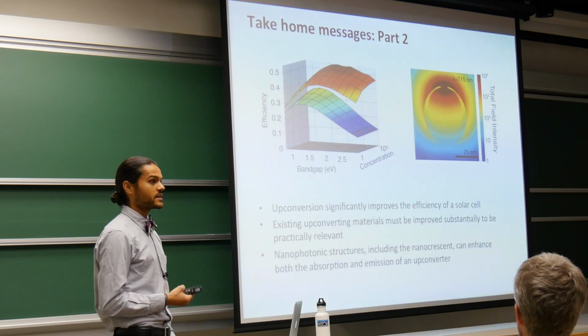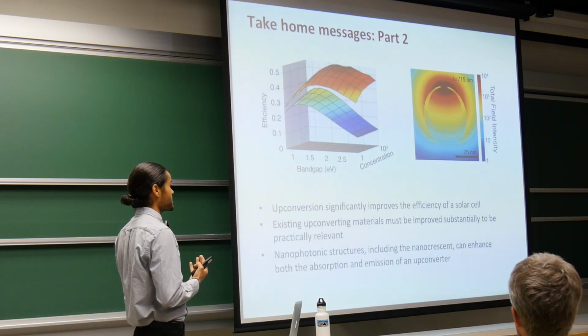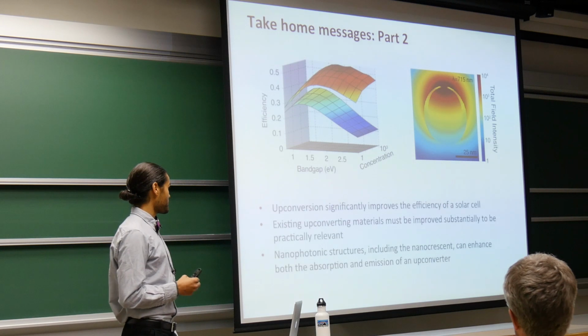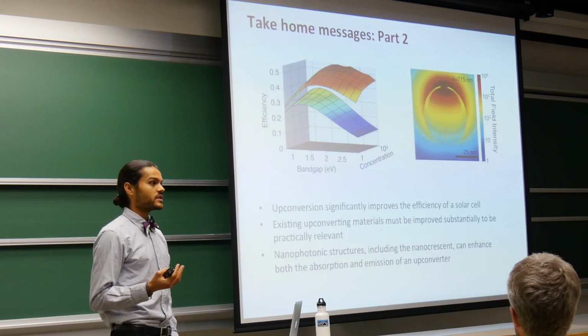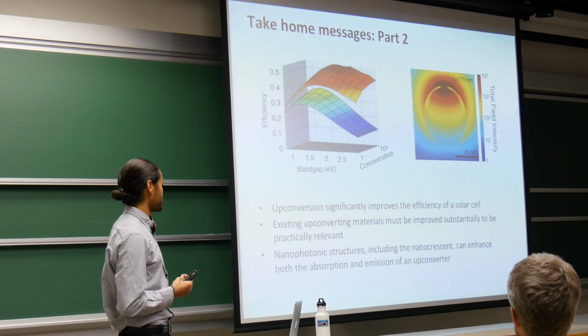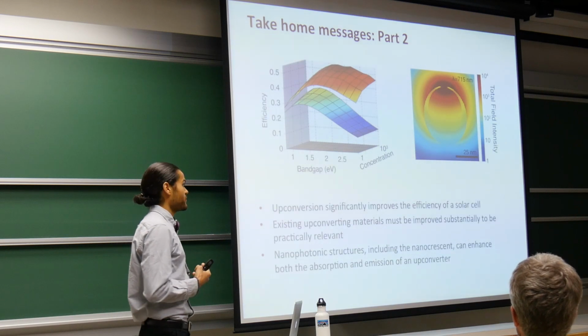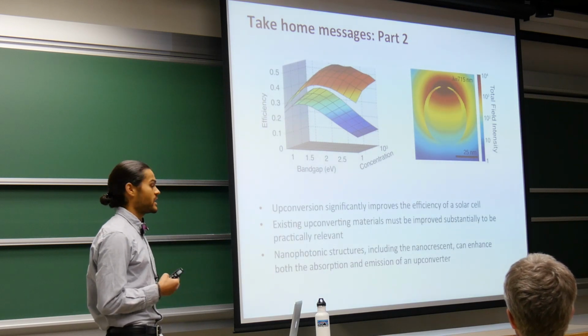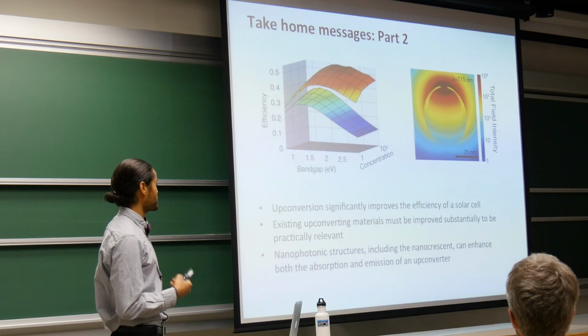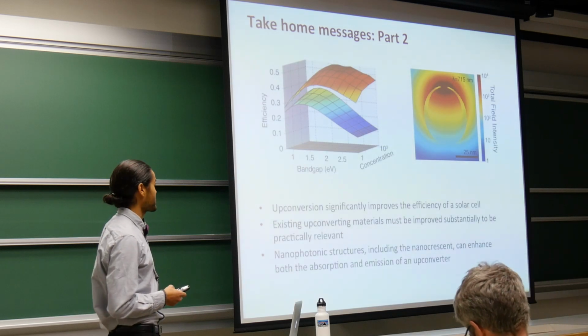So to wrap up this second section, I've showed you how upconversion can significantly improve the efficiency of solar cells, but that existing materials really need to be boosted before they become practically relevant. I've also introduced a nanophotonic structure, the nanocrescent, and showed how that could possibly enhance both the absorption and the emission of an upconverting system.